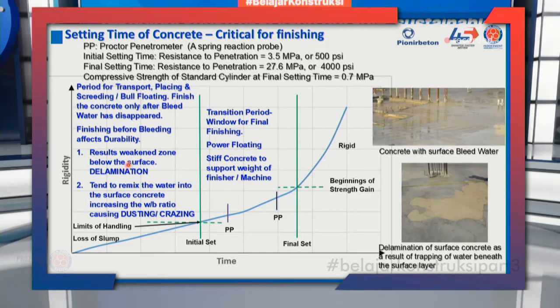The other thing is, you have to wait until all the bleed water comes out. If some bleed water is trapped below the top surface, then we end up in what is called delamination. Because the bleed water is below the top layer, it has to come out. Where does it have to go? It will push up the top layer. So we get a delamination.